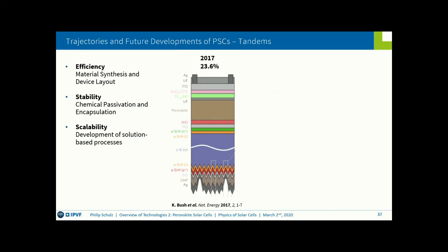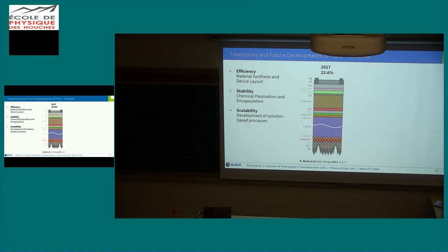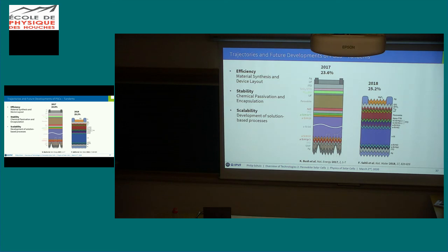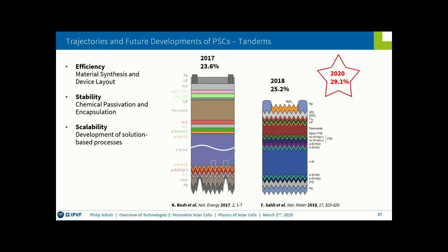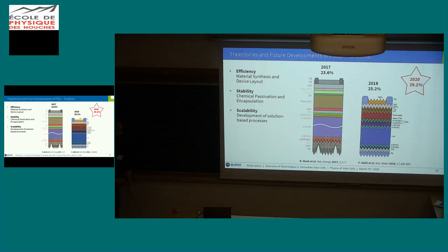Now, this is the summary of everything. We are hunting for efficiency and stability: efficiency by integrating perovskites in tandem devices, stability by chemical passivation but also encapsulation, and scalability. We moved from 23.6% for this silicon perovskite tandem device to 25.2%, and now, as I said, earlier this year, 29.1%. Of course, there are the limits we heard about, particularly the Shockley-Queisser limit earlier today, but it's unclear what is currently the limiting step here.